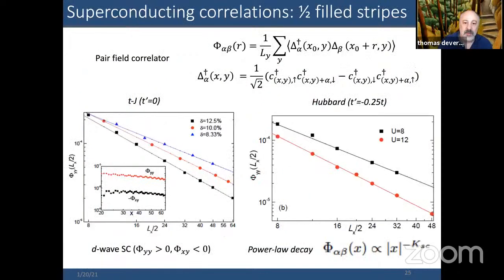If you then look at the superconducting correlations, again delta-delta dagger for distances down the chain. Now this is on a log-log plot, and you can see for different values of doping that it decays as a power law rather than exponential, in both t-J and in Hubbard, there's two values of U on the right-hand side. And it's D-wave like, meaning that the bond-bond correlations change sign under a rotation of 90 degrees. Of course, the cylinder breaks C4, so it's not truly D-wave in that sense, but it's D-wave like in that there's a change of sign. And if you fit the power law decay, you can define an exponent K_SC for how quickly the correlations die off as a function of distance.